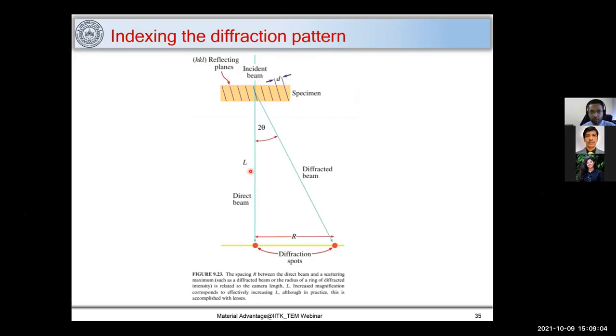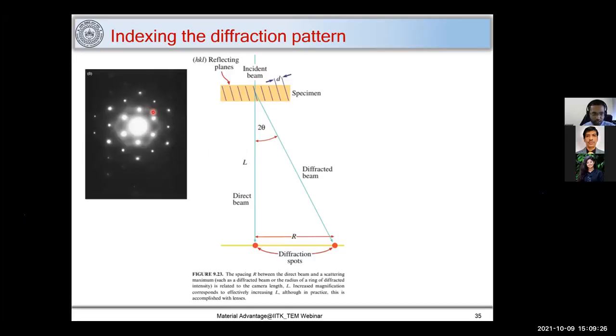Let me come to the main important point here, which is indexing the diffraction pattern. To do that, first you should know your camera constant. So you have an incident beam which interacts with the specimen, and specifically these planes, which have a d-spacing, and this is the camera length, and this is a diffracted spot. Based on this geometry, you get this diffraction pattern, and you find out the radius, this r, from your transmitted spot to a diffracted spot.